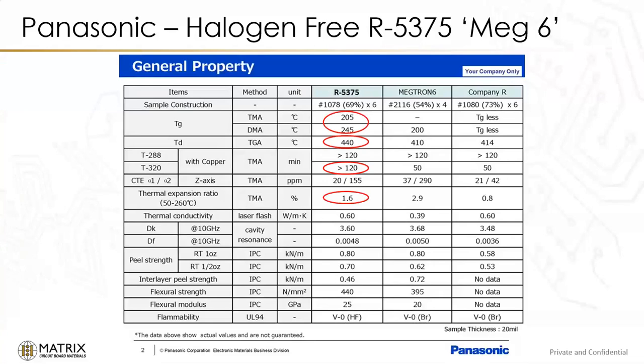So a low Z-axis expansion, a high thermal conductivity, higher than Meg 6, for those that are interested in that, could be a benefit as well. Very similar DK/DF values to what we're used to seeing with Meg 6, so that fits into that same category. And then, of course, being halogen-free is the bonus. So the Meg 6 thermal and electrical performance that we're used to, but with a V0 flammability rating with halogen-free. So we're looking forward to seeing that as it becomes more available.